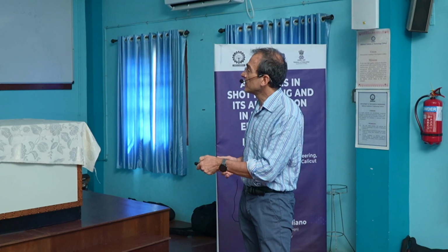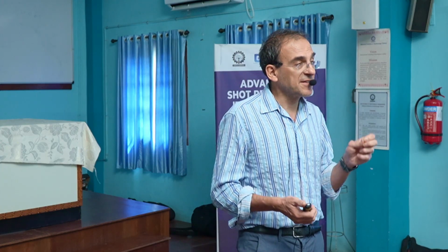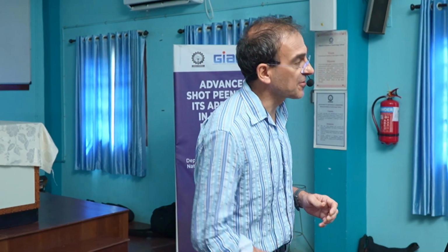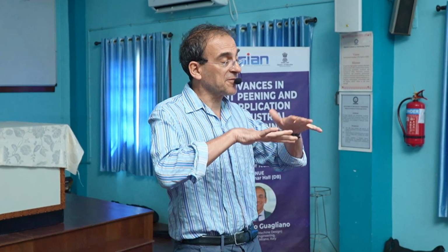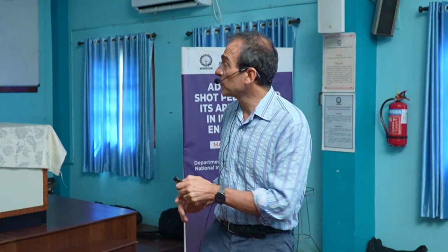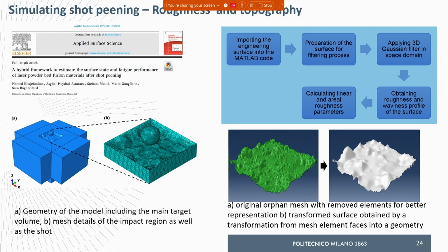And the way the roughness is introduced comes from the digitalization of the real surface by means of AFM. The data defining the surface, so we can reconstruct a digital surface, also by using some filter to avoid numerical singularity.